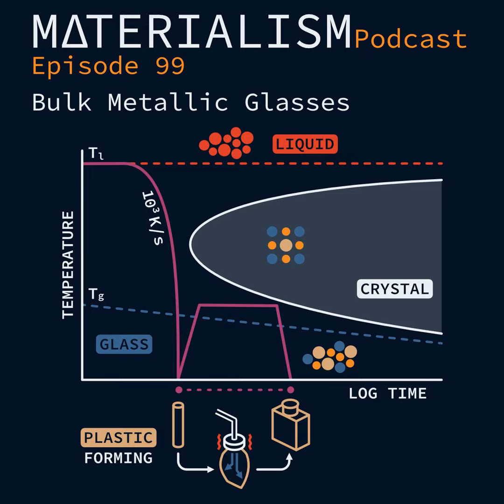The word I kept seeing over and over again in the literature is this idea of frustrating the formation of a crystal by adding multiple elements, elements with very different sizes, things that are going to obstruct and maybe just give you a little more time to cool past that crystallization point. Yeah, and as the structures get more and more complex, one of the points I saw was that the energy stabilization relative to amorphous gets smaller. And so the driving force for crystallization is also reduced.